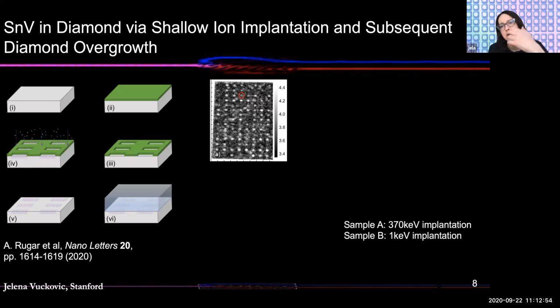shift. So what we want to do is avoid all of these processes that are leading to degradation of the crystalline structure of the material, but at the same time insert color centers in a regular grid. And in collaboration with Nick Melosh and Zhixun Shen at Stanford, we have developed this process of shallow ion implantation and subsequent diamond overgrowth. In this process, we basically start from high purity diamond. We mask it using traditional electron beam lithography, then perform low energy ion implantation. That's why we call it shallow ion implantation.